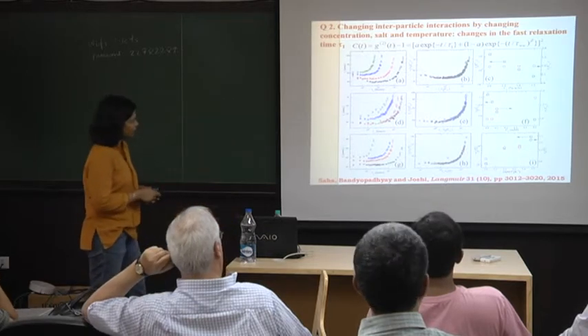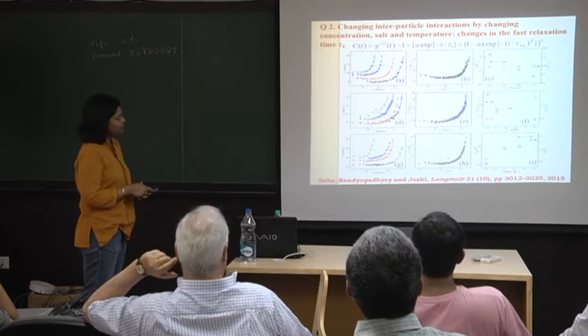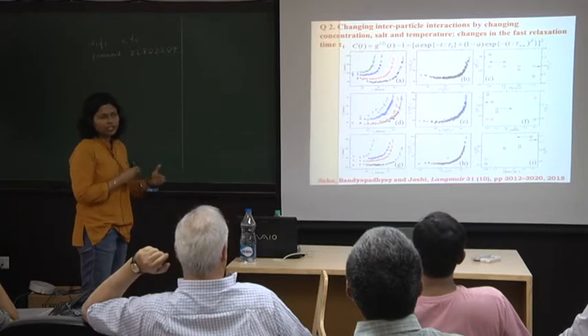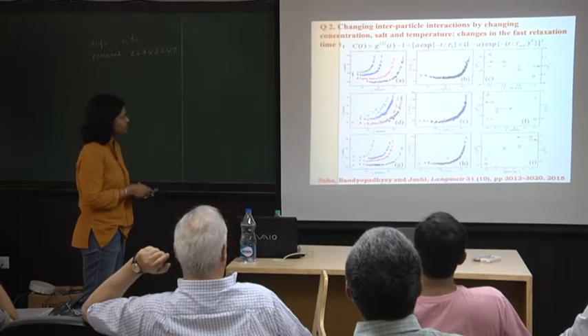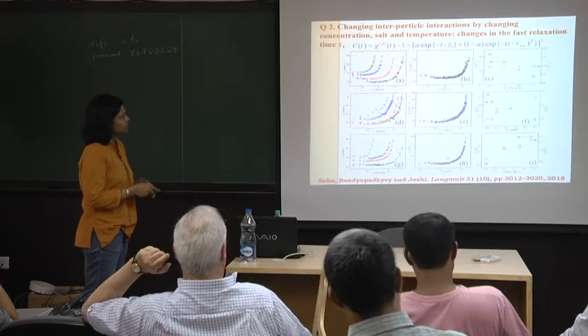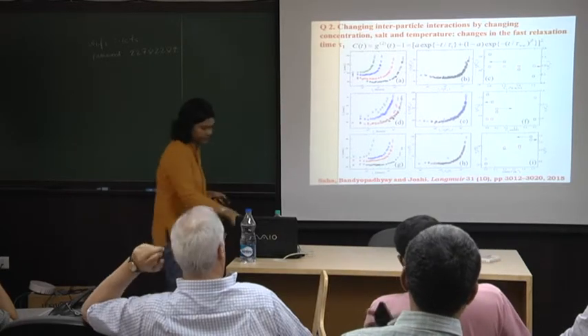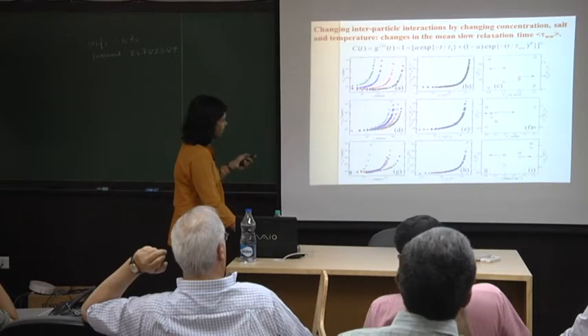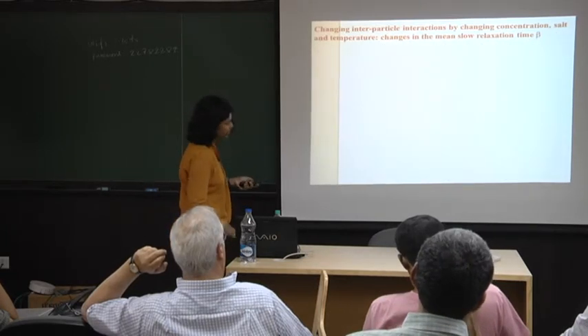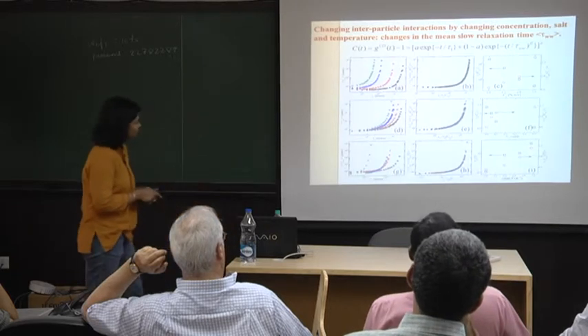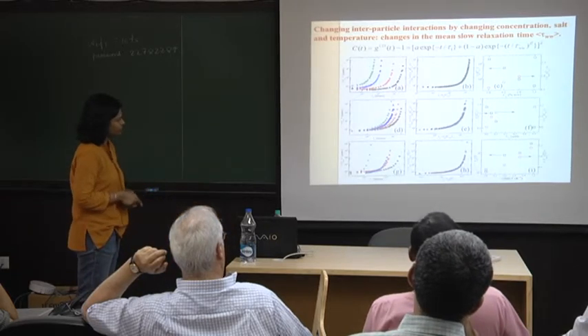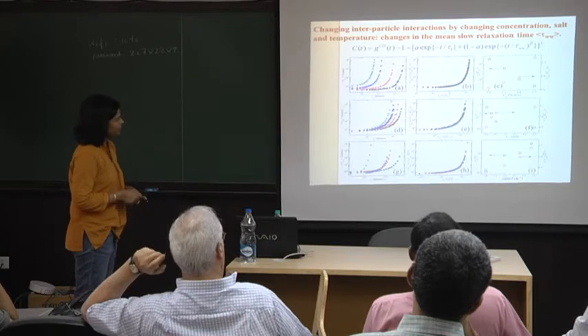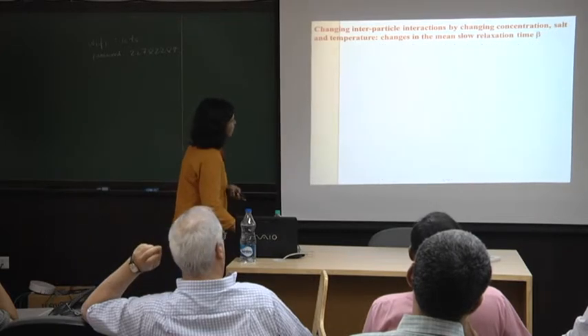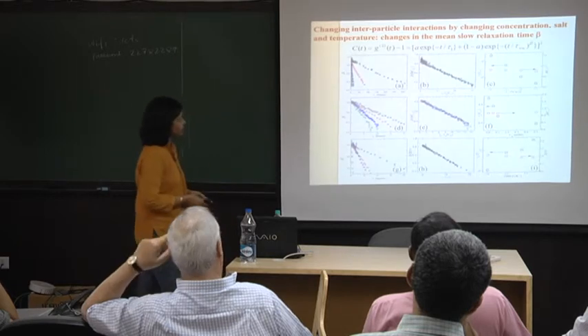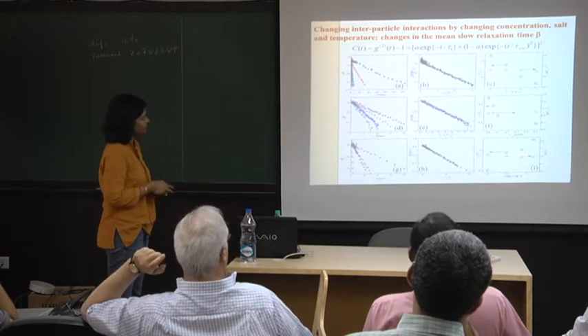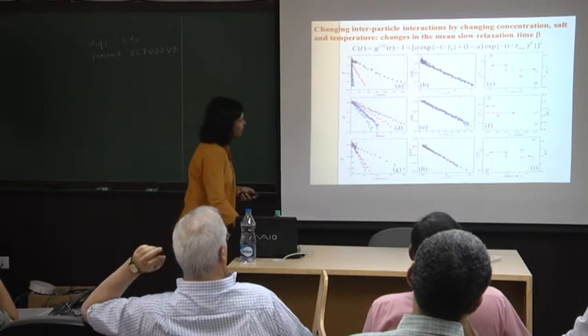Okay? So again, you can take all this data, you can scale it. We've used the same functional form for fitting. We are normalizing by the same coefficients, and here you can see that all our data overlaps nicely. We've also done the same thing from the DLS data, where we've calculated the slow relaxation data. So here again, with concentration increasing, salt increasing, temperature increasing, they overlap very nicely. Same for the stretching exponent here. Again, concentration increasing, salt increasing, temperature increasing, works very well.